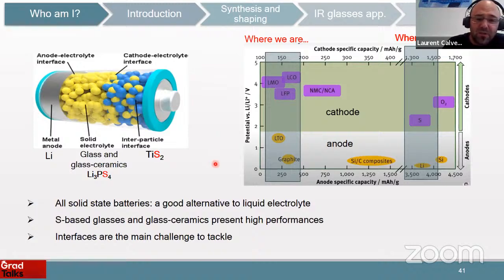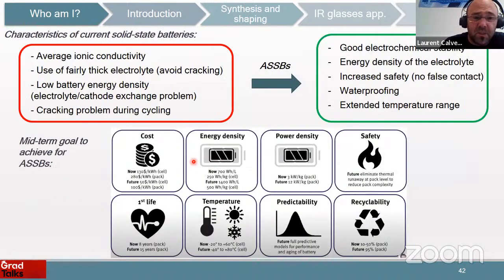So solid-state batteries also appear as a good alternative to liquid electrolyte. Sulfur-based glasses and glass ceramics present very high performances because they are using lithium, but we still have some challenges to tackle, like the interfaces between the metal anode and the solid electrolyte. So for now, with the current solid-state batteries, we obtain pretty good ionic conductivity, but not as good as ionic liquid. We use a very thick electrolyte, which is not good. We have low battery energy density, and sometimes it's cracking after cycling. However, we have a good electrochemical stability. We have an energy density which is pretty good also.